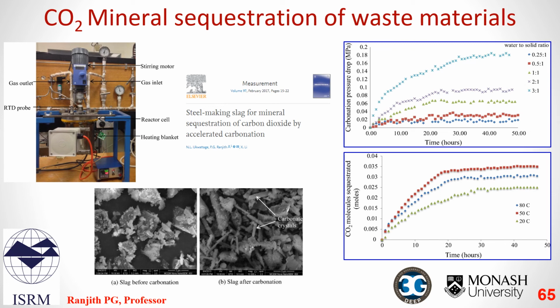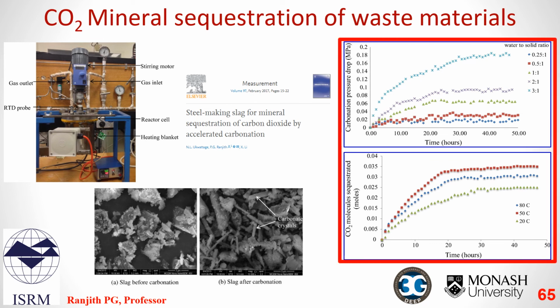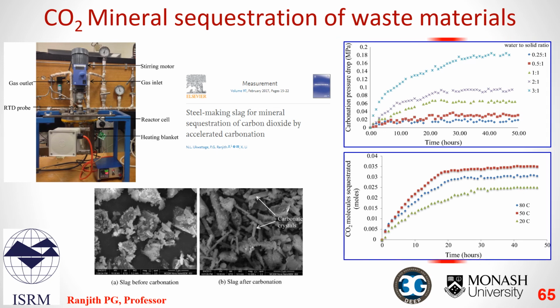We also evaluated CO2 sequestration into steel slag. It would reduce the demand for commercial CO2 sequestration and significantly reduce the required energy and cost. Here we can see that with the increase of water to solid ratio, the ultimate sequestration is significantly enhanced. Potentially, this process can store around 30 kg of CO2 in 1 ton of slag. Please visit our paper published in Measurement Journal.